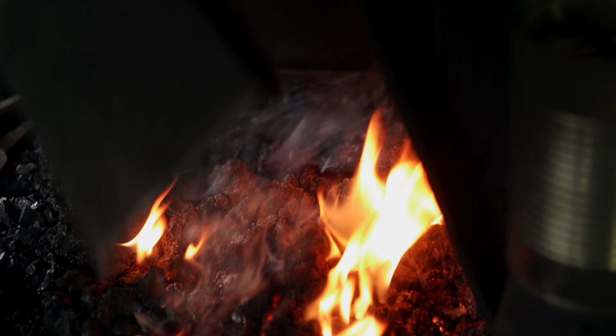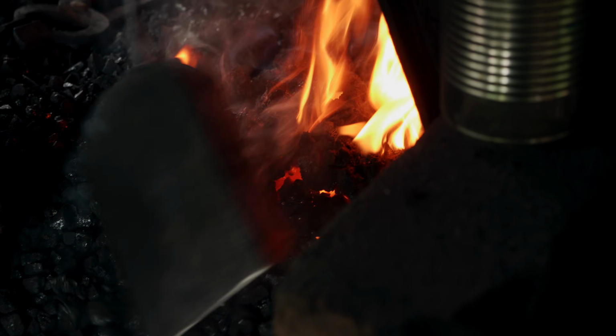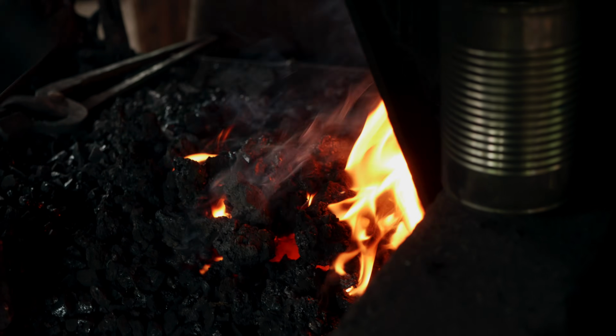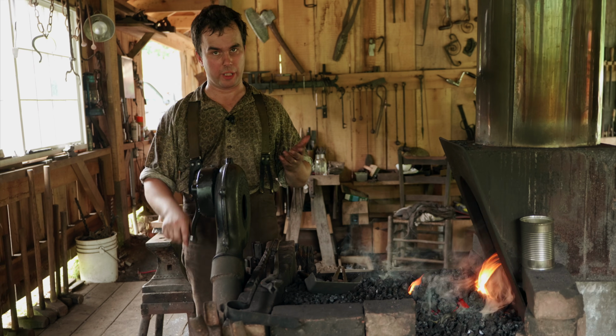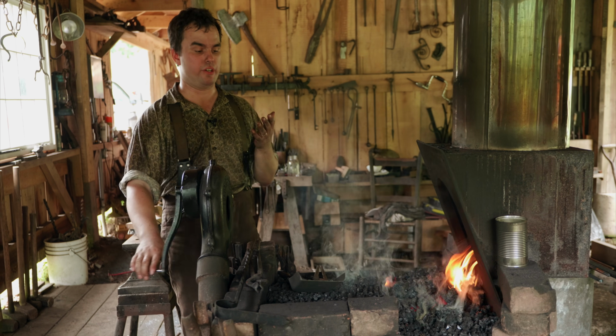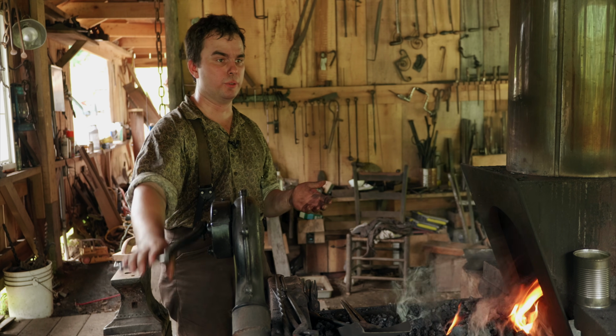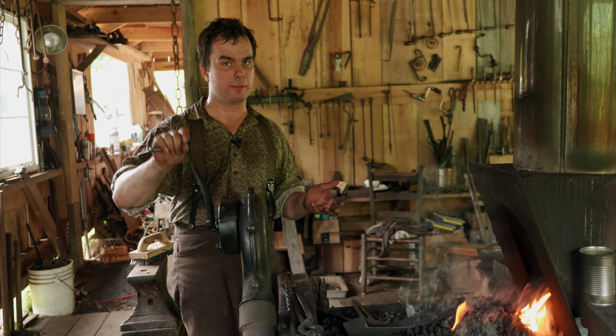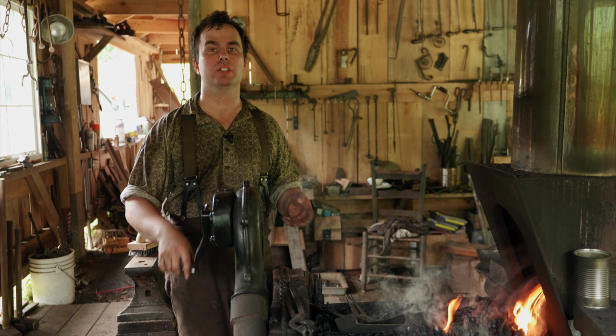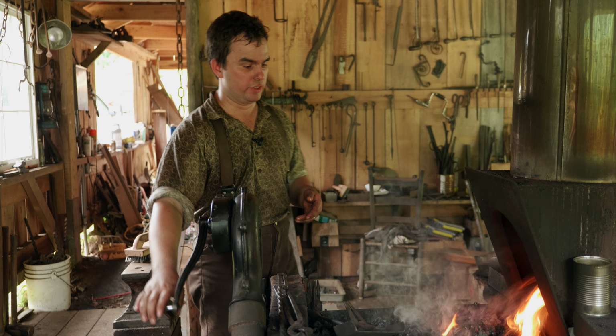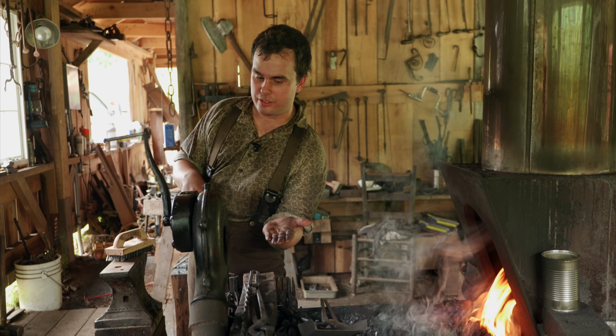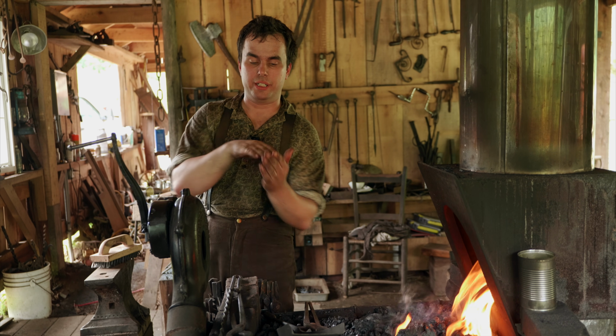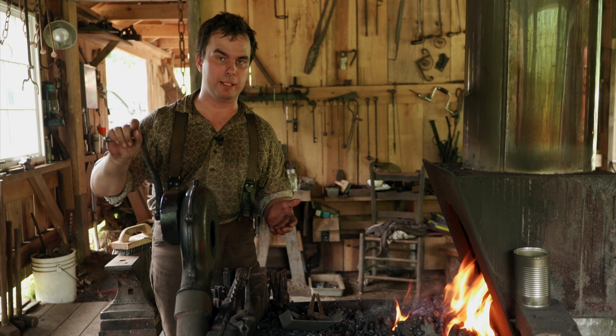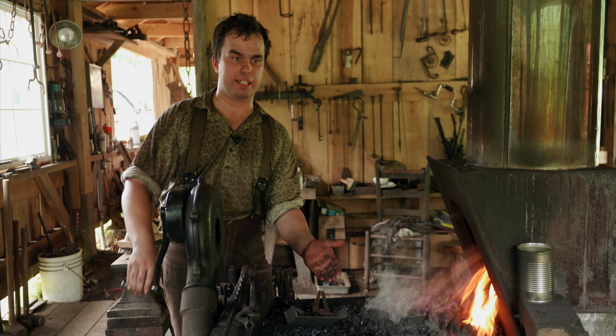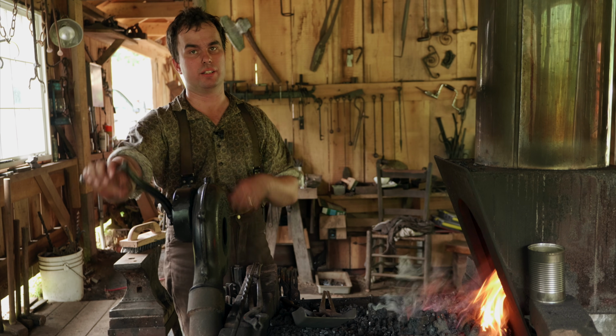I just want to make sure that I don't bump that little nubbin of steel because it's just sitting there in position. All right, we're going to bring it to forge welding temperature. Wrought iron forge welds at a much higher temperature than the carbon steel. And the carbon steel, at forge welding temperatures, you're getting really, really close to burning the steel and ruining it. So it's a good situation that our wrought iron's on the bottom and our steel's on the top, and that way we can put a pretty good blast of air to the fire, which will make the iron get hotter quicker than the steel on top, which is perfect.